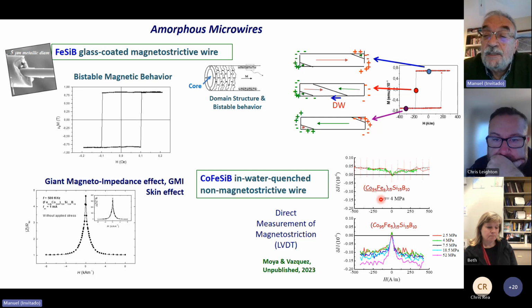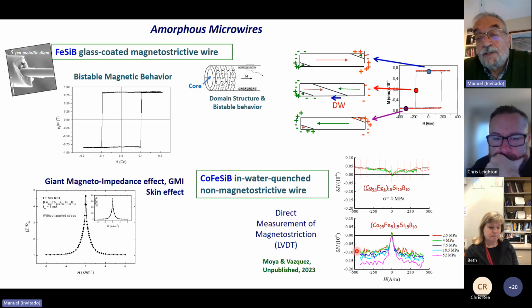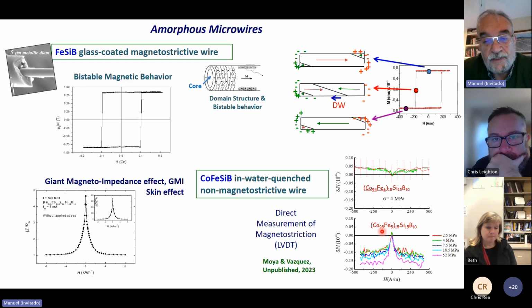But if we change just 1% in the composition of iron or cobalt, you see the magnetostriction changes sign and goes to negative. Also very small, maybe not so small, but also really very small. So it is important for me to emphasize that we can tailor the value of the magnetostriction, going through the zero value, making small changes in the composition.